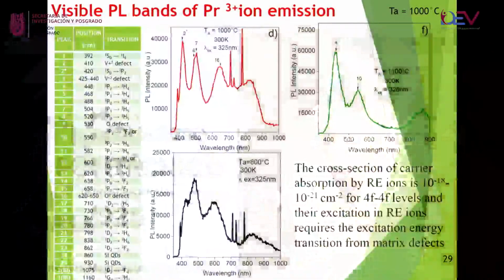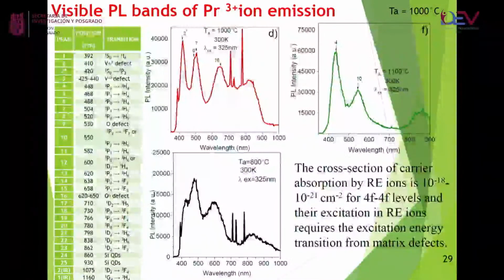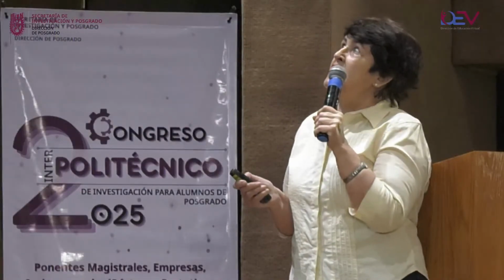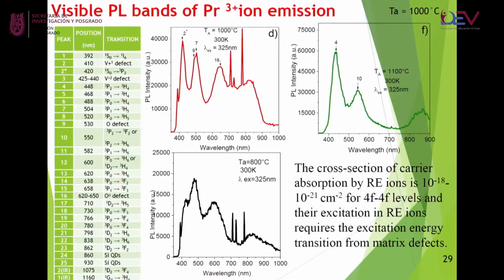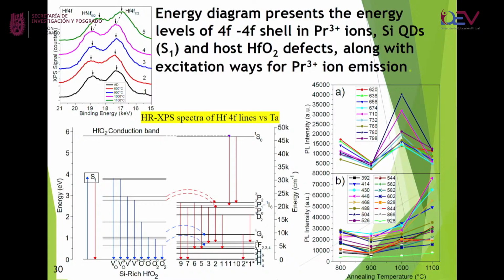You could see here a low energy photoluminescence band connected with a defect which is an interstitial oxygen atom or molecule. But when the temperature increased, oxygen disappears and vacancies appear in the material, and the photoluminescence spectra change very much. The low energy band disappears, and the higher energy band increases in intensity. We propose the model that low energy light is excited by oxygen interstitials, and higher energy light is excited by vacancy defects in hafnium oxide.